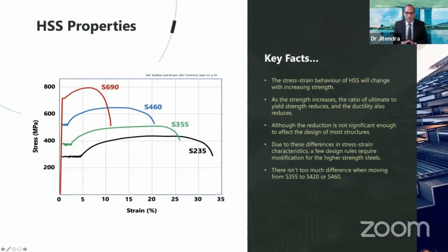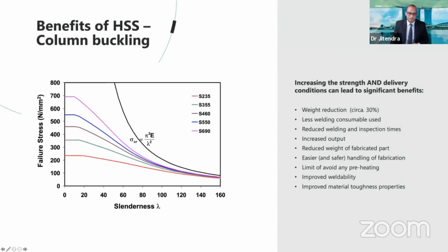This gives a schematic of the stress strain curve behavior as we go from 235 all the way up to 460 and 690. You can see that, yes, there is slightly less elongation, in this particular case it's plotted as strain, and we can see the work hardening potential is also decreased. But overall, the stress strain behavior remains the same, and there isn't too much difference as we go from 235 to 355 to 460 in the main, as I have stressed.